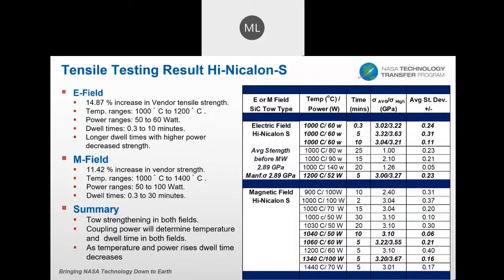In summary, the tow strength is strengthened in both fields. Coupling power will determine the temperature, determine dwell time in both fields. As temperature and power rises, dwell times decrease. And here we'll really see some nice numbers for the average strength. And we see that at 1340 degrees C, 60 watts, 5 minutes, here at the bottom of the table, really produce some of the best results for strengthening the fiber tow. Next slide, please.